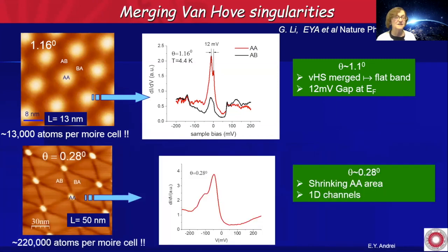Then we go to a smaller angle, 0.28 degrees, and again the band becomes wider. But because the Moiré period is so large, the AA region now can shrink. So you see these AA regions have shrunk dramatically, and they're connected by these one-dimensional channels, which turned out to be very interesting, but I'm not going to go into that today.